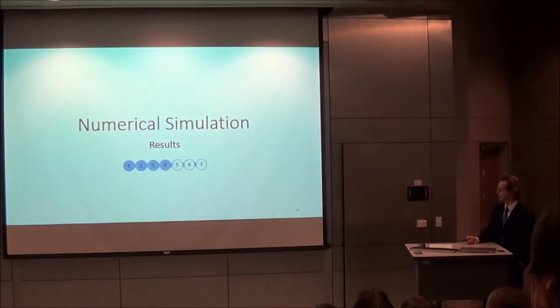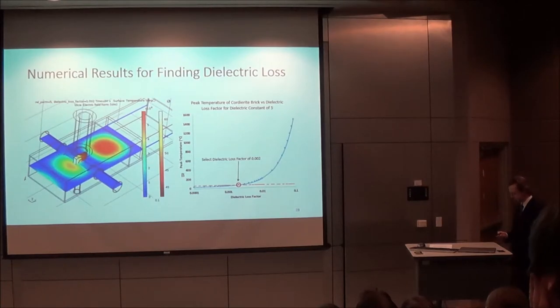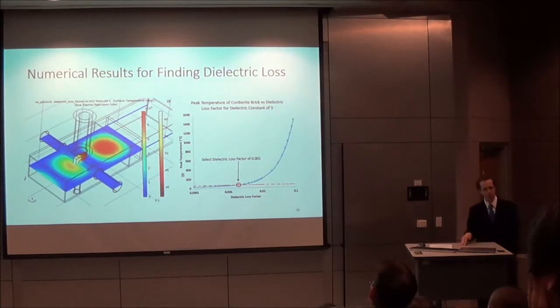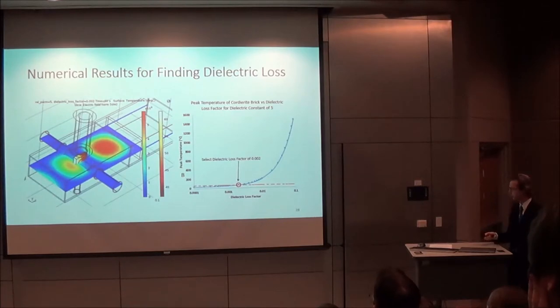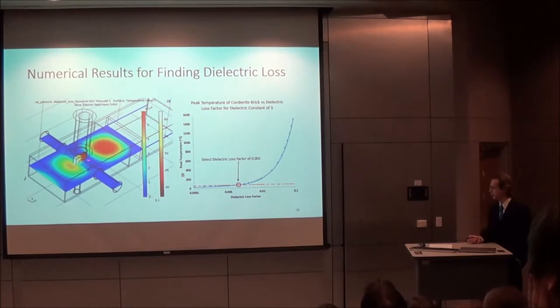So the results of this numerical simulation work. First of all, the evaluation of cordierite and how it heats in the joining chamber in order to find the dielectric loss factor is shown with this diagram. You have electric field distribution, taking an XZ slice through the waveguide, and then temperature in the dielectric material. And you can see where the electric field intensity is greater close to the target, there is a higher temperature in the target, and it's not very thermally conductive, so after 60 seconds there's still a decent thermal gradient across it.